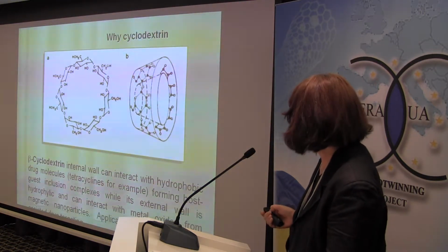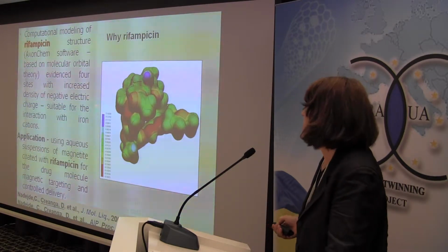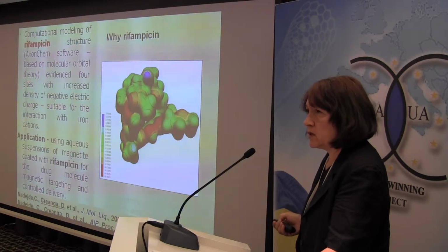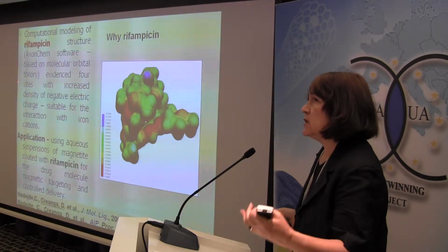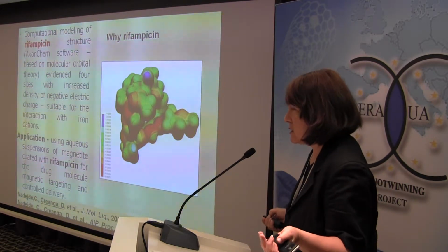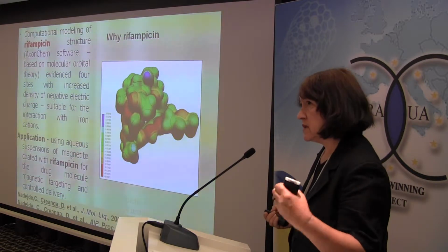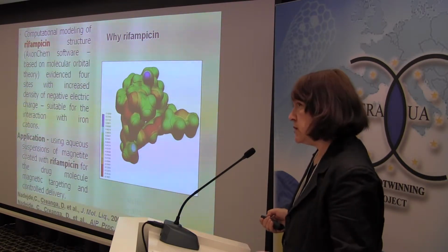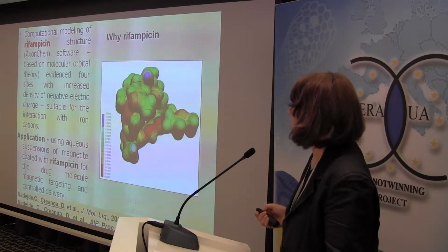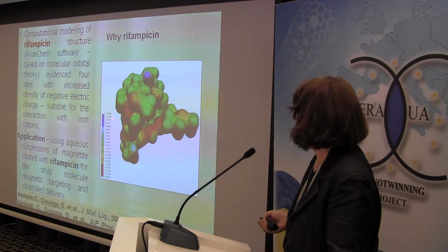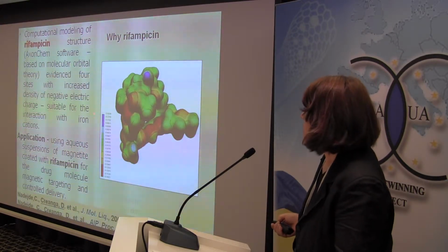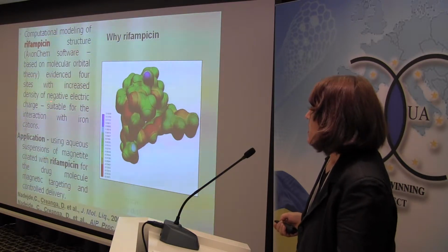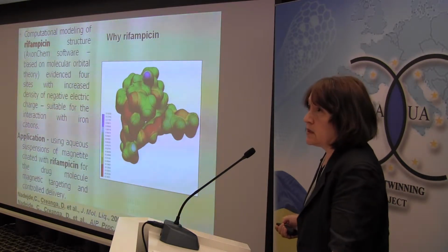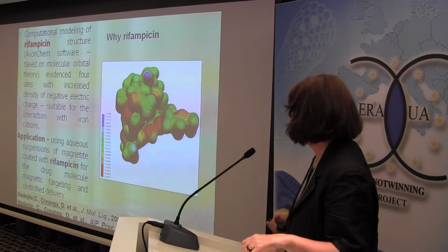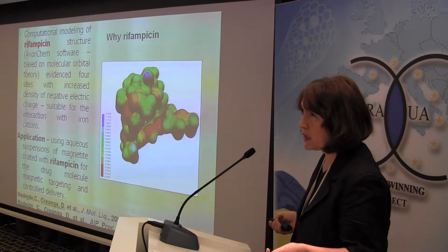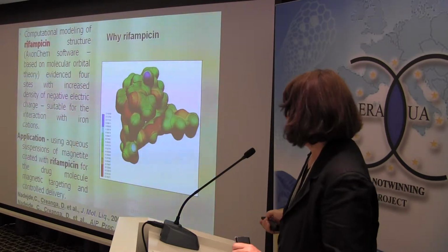Why rifampicin and why cyclodextrin, I am trying to tell shortly. This is a strong antibiotic, very useful in lung disease treatment. But being a strong antibiotic, at the same time, it affects all the other cells of the body. So it would be better to target it directly to the lung. This could be done with magnetic carriers, like the magnetic nanoparticles we prepared. How to attach it to the magnetic nanoparticles? The computational modeling revealed that there are some sites with an increased density of negative electric charge, and we believe that on these sites the cations from the magnetic nanoparticles were attached.